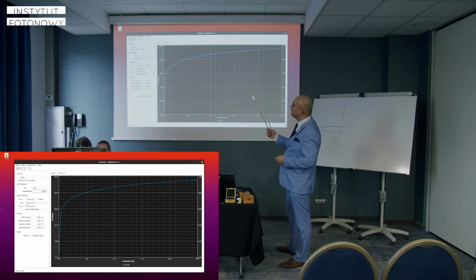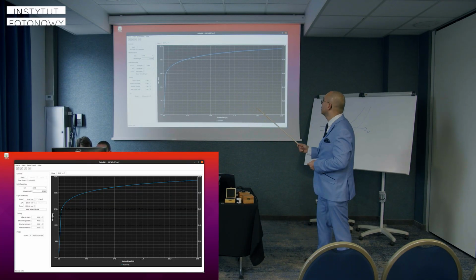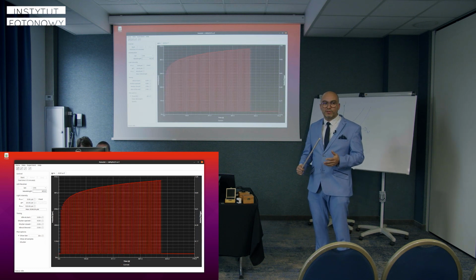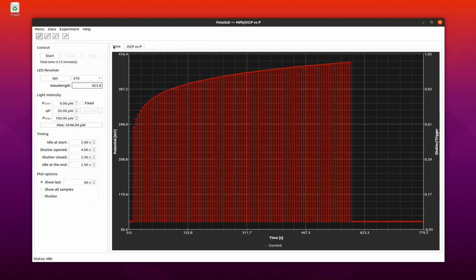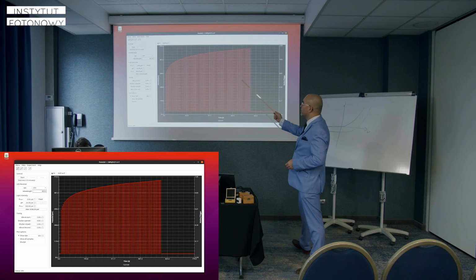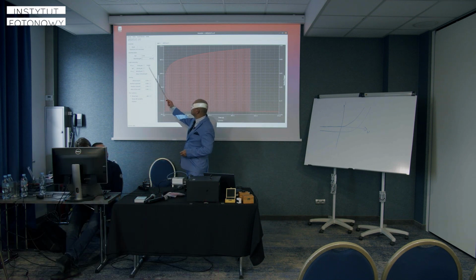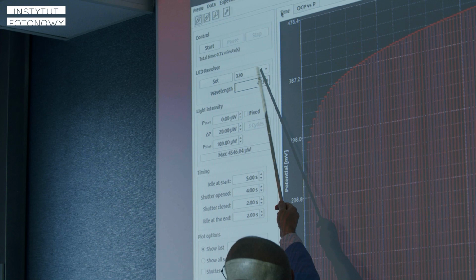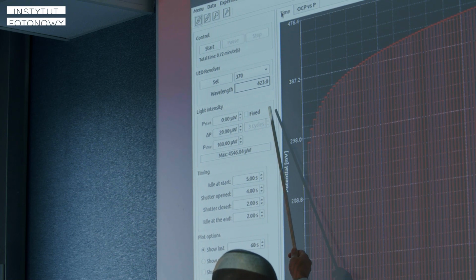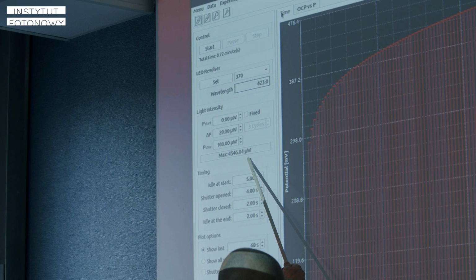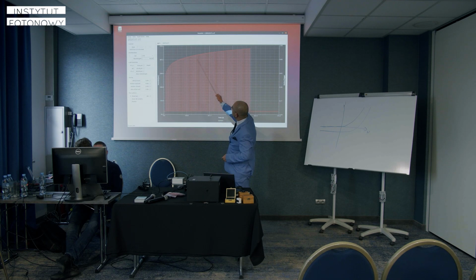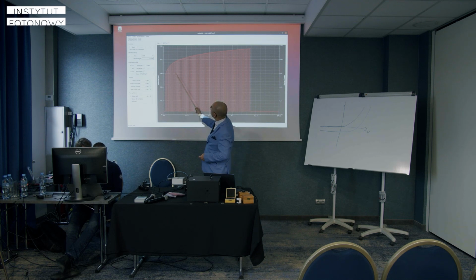So again, we can select for which wavelength we perform this experiment, because for different wavelengths the sensitivity of our sample may be different. We define the range of light power from, say, 0 microwatts up to the maximum available power for this LED at this wavelength, which is 4,500 microwatts, so 4.5 milliwatts, with a step. The denser the step, the better and more fluent the profile is.